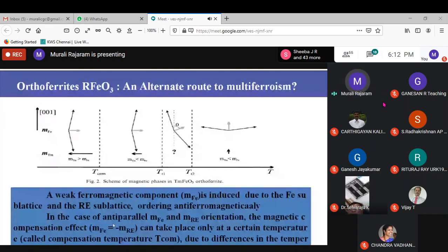There are two magnetic ions. Rare earth ions, as I said in the periodic table, like gadolinium, neodymium or europium, produce a magnetization. So the rare earth can be a magnet. The iron ion also can have a moment. The most interesting thing is that these are all antiferromagnetic materials. Interestingly, these are not proper antiferromagnets. They are called canted antiferromagnets because the spins are slightly turned, so that induces a ferromagnetic moment. The iron ions on different lattices are not anti-parallel but slightly twisted, so that induces a ferromagnetic component in one direction.